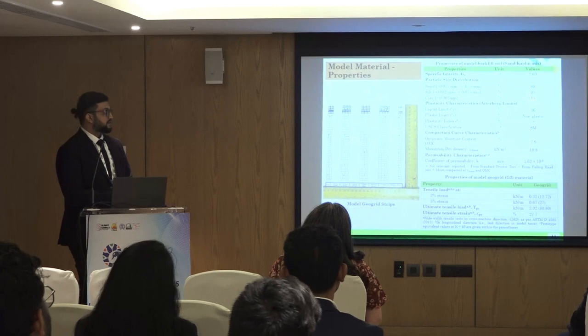Another reason is that we developed a laboratory sand kaolin mix, which is 4:1, 4 parts sand to 1 part kaolin. When we looked at the grain size distribution, we can see we have 20% fines, which is slightly above the stipulated. So it actually suits our marginal backfill or a low permeable backfill. That's what we were targeting.